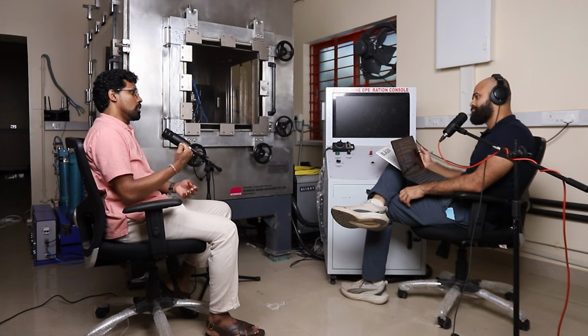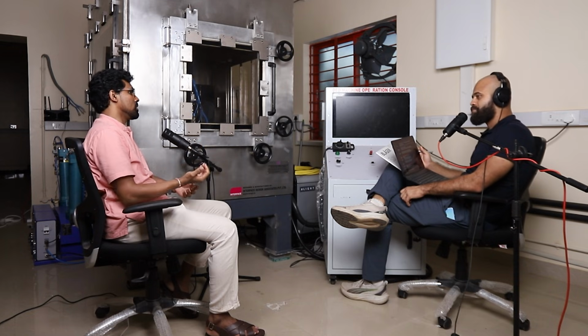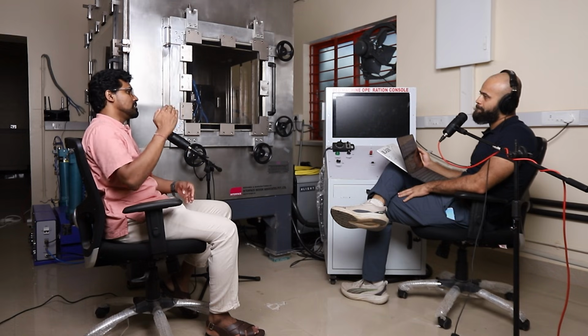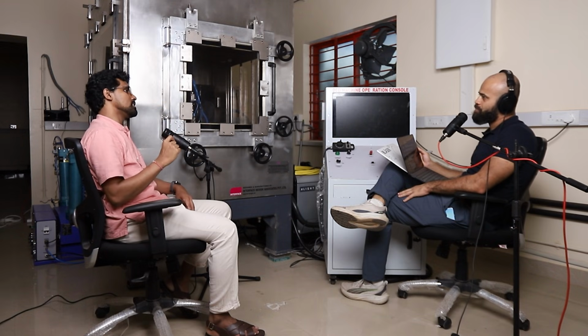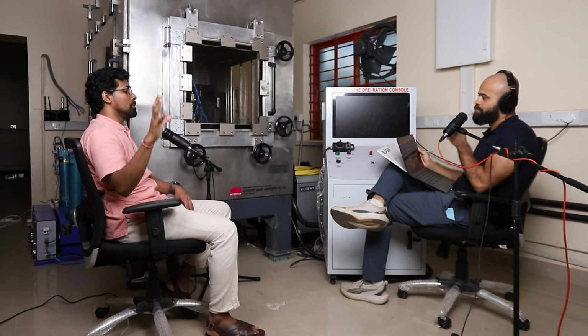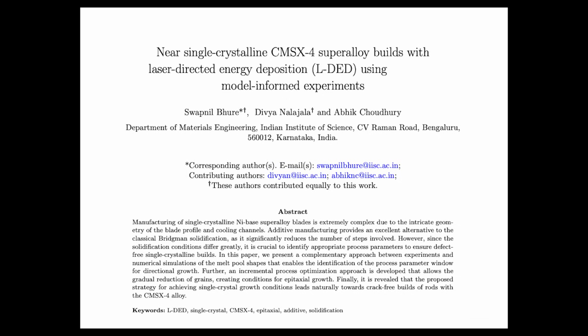You might be scanning at some velocity, but what is the velocity at which it is solidifying, or the dendrites are growing? And then the temperature gradients at that interface. So these two factors, the solidification velocity and the temperature gradient, can tell a lot about the microstructure that you are going to get. In my research, as you have seen from my paper, we are working on single crystal alloy. So what we are aspiring to do is to 3D print something which will have a single crystalline microstructure. Now, additive manufacturing in itself has all the conditions that are needed to get a polycrystalline or a columnar growth. Getting a columnar growth inherently happens, but getting a single crystal, that's the challenging part. So we try to establish a relation between the shape of the melt pool, the solidification velocities and temperature gradients, and the microstructure.